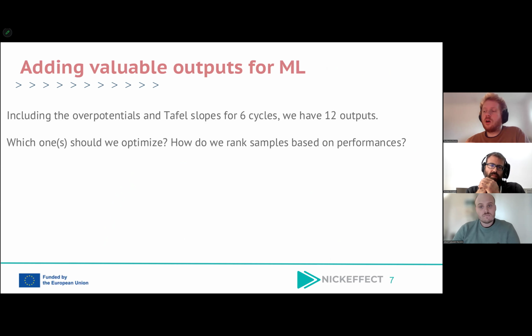And then the question is, how do we compare two films? How do we know which one performs the best? Because we have the overpotential and the Tafel slope for 6 cycles. That means we have 12 outputs. So we may have one Tafel slope that is better for a film, and then the potential is worse for this film. So how do we actually rank the films, and how do we quantify the performances with a single number that's easier to interpret?